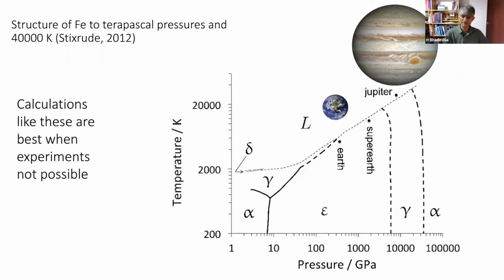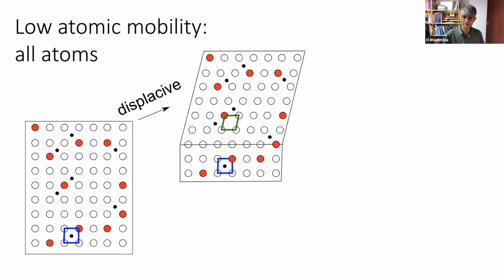Now, between all these allotropes, and there are actually more when you make thin films, there are different ways in which you can get solid-state phase transformations. The simplest is a displacive transformation, in which there is absolutely no diffusion, but a physical deformation changes the shape of the unit cell. These are interstitial atoms, and even the interstitial atoms have not moved their relative positions. And there is obviously no composition change at all in such a transformation.